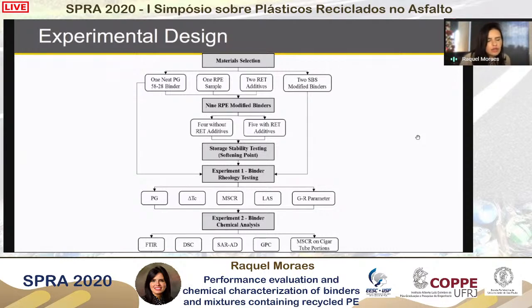And after the storage stability results, we select the binders that would be further evaluated in terms of rheology and chemical analysis. For rheological evaluation, we use Superpave performance grading, delta Tc, multiple stress creep and recovery, the linear amplitude sweep, and the Glover parameter. And for the chemical analysis, we perform FTIR infrared, differential scanning calorimetry, the SARA fractions of the asphalt, gel permeation chromatography, and we also did the MSCR tests on the portions of the cigar tube after the storage stability testing.